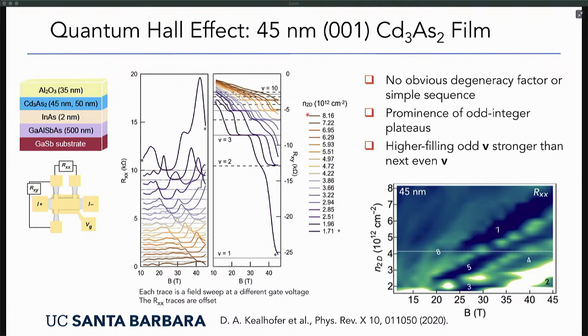What you get is a quantum Hall effect that is quite unusual. If you look at the first trace, you see a very strong nu equals 3 Hall plateau, and nu equals 2 is almost not present. At other gate voltages, you get a nice nu equals 2 plateau and also nu equals 3, and in some cases nu equals 3 is almost absent. So there's no obvious degeneracy. A typical lifting of a degeneracy would mean that nu equals 2 is much more pronounced than nu equals 3, and that's clearly not the case here.